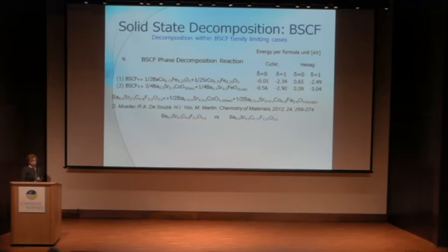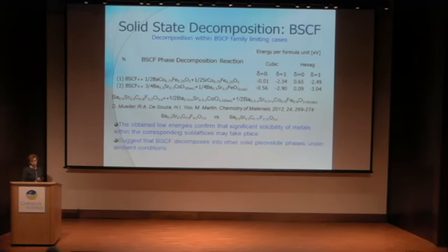It also shows that the same reactions can occur in cubic phase and hexagonal phase, with vacancies and without. But the energies are different, and the obtained low energies for this kind of disorder confirm that significant solubility of metals within the corresponding sublattices may take place, which was kind of an explanation for experiments and what they saw in loss of performance of the materials in fuel cells.